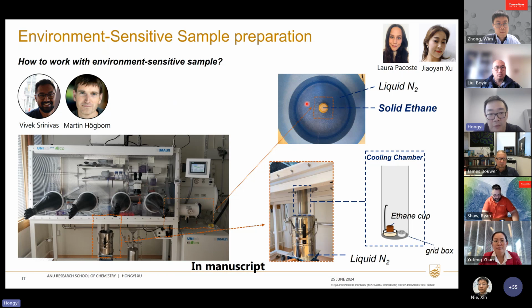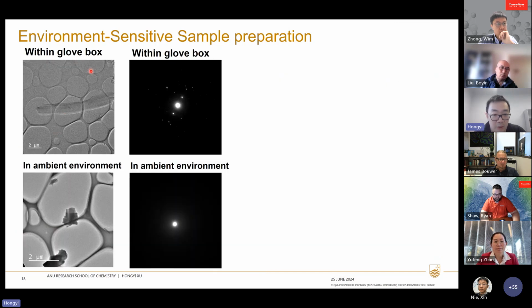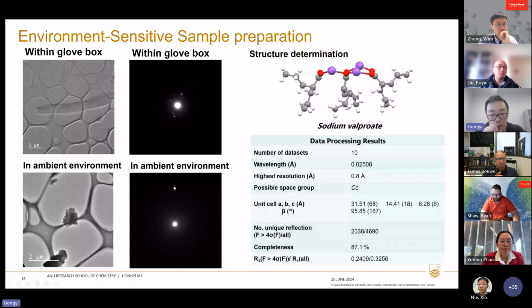So this was done for small molecule, but the purpose of this machine, actually Laura is working on, is to trap the intermediates of a redox reaction in an enzyme. So we're actually studying enzymes in different states, oxidation states, and then look at the charge of the metal ions in the enzyme. Right, so this was within the glove box. We can see beautiful diffraction. And then if we do it in air, you see that even the crystal morphology changes very rapidly, and we don't see any diffraction, obviously. So this is one way to actually work with very environment sensitive samples. So for lithium-ion battery, I think this will be a very nice workflow.